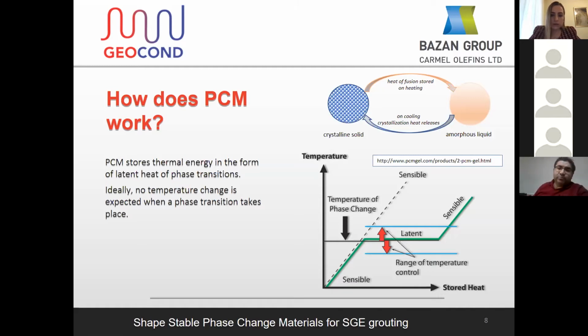Ideally, melting and crystallization temperatures should be the same, and when the phase transition starts, the temperature should stay constant. In reality, organic PCM usually show a melting temperature a little bit higher than the crystallization one because of so-called overcooling, and there are small temperature changes during the observed phase transitions.